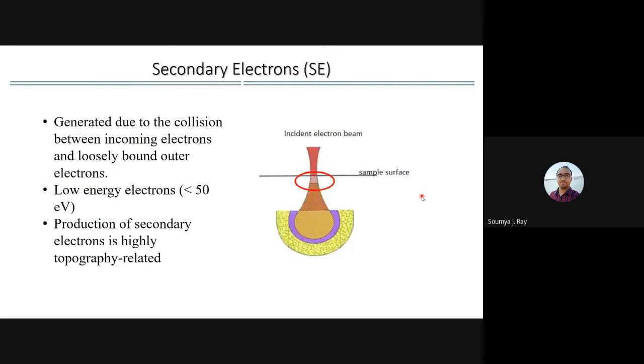Now let us see what these different types of electrons are. The first is the secondary electron. What happens is that you have an incident electron hitting your sample surface. There will be some collisions. You can imagine these electrons as carrying some energy. Essentially this energy is being absorbed by the sample, and the sample itself gets excited and releases another electron, or let's say more than one electron. Since this is a different electron released from the incident one, it is called the secondary electron. The primary one is the incident one, and the one released by the sample is the secondary one. Typically they have very low energy, less than 50 electron volts, and this production is highly topography related.